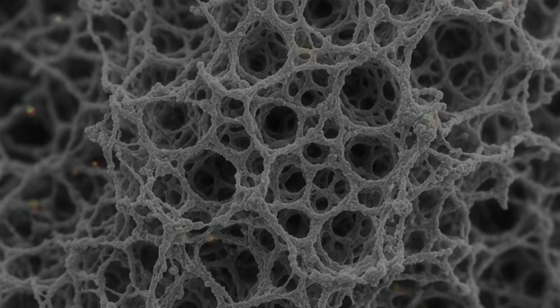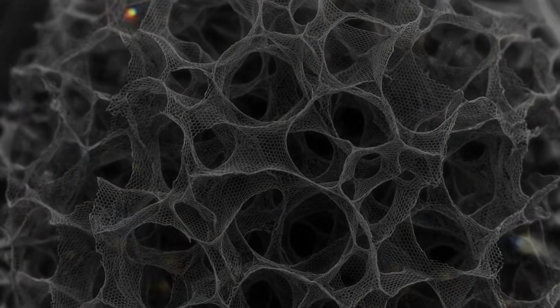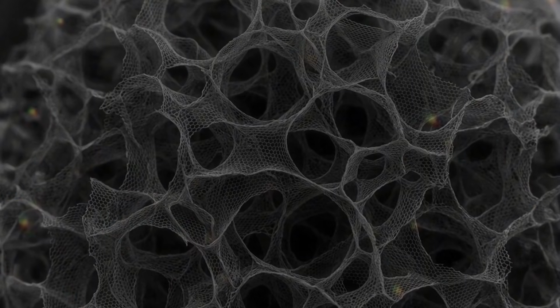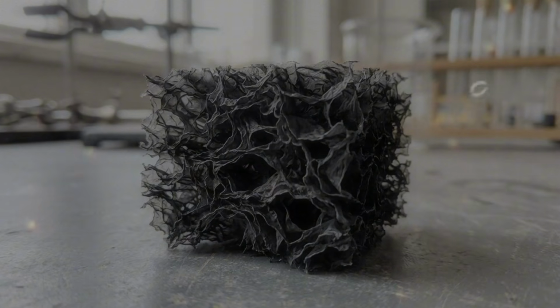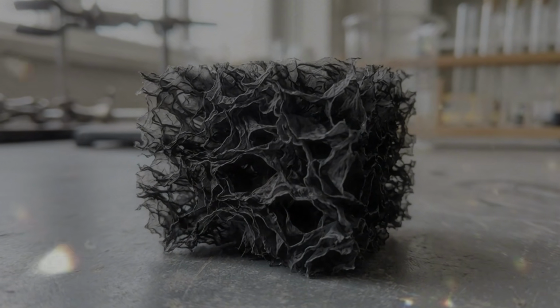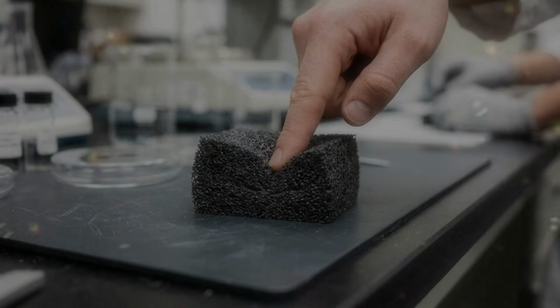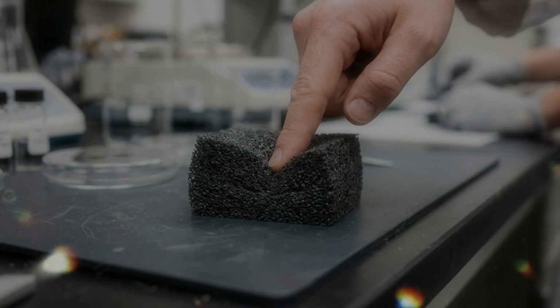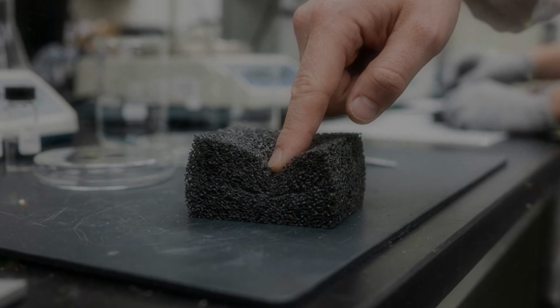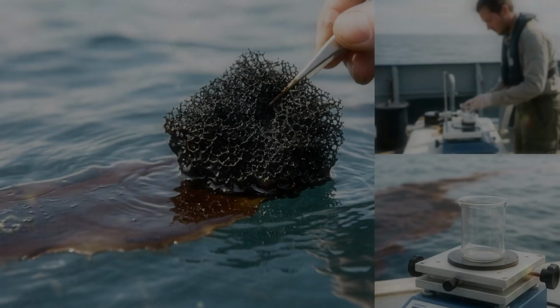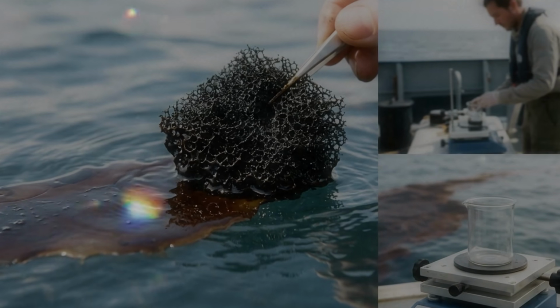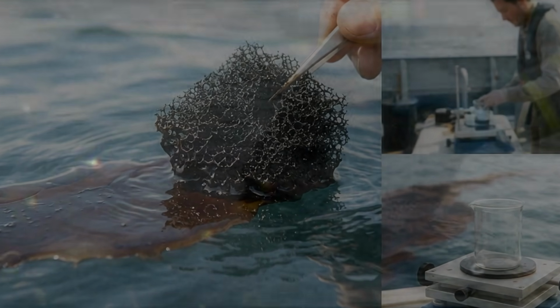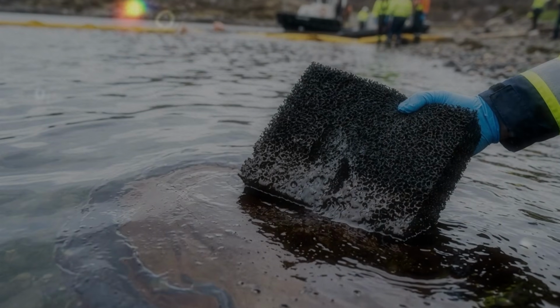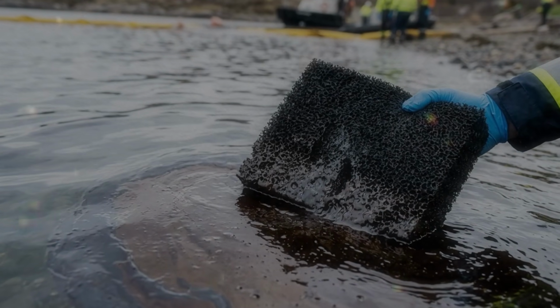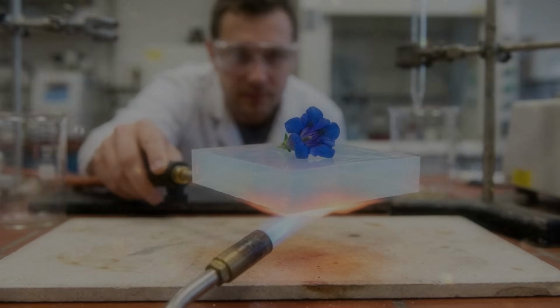Defects also shape the outcome. In ordinary conversation, a defect sounds like a mistake that should be removed. At very small scales, defects can sometimes be useful. A missing atom or damaged bond can create a site where a molecule attaches. An opening in a graphene sheet can allow ions to pass through. Oxygen-containing groups can help a sheet interact with water or bind to another material. Too many defects weaken the carbon network and reduce conductivity. Too few may make the sheets difficult to process. The goal is often not perfection, but controlled imperfection.